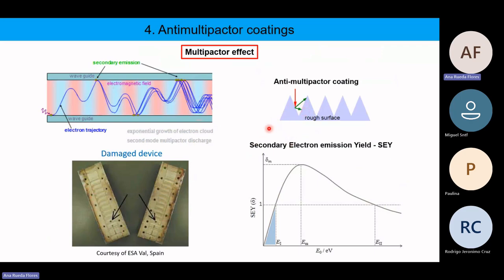The way to measure this phenomenon is by measuring the secondary electron emission yield as a function of the energy of the primary electron. And typically, this is the shape of the curves, and there are two parameters that you want to tune. One is the maximum of the curve. You would like to have it as low as possible. And the second important parameter is the crossover energy with the value 1. Because for energies lower than that crossover energy, you have, on average, less than one secondary electron emitted per primary electron. So the phenomenon disappears.